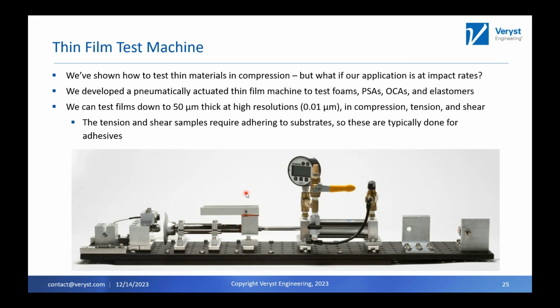So I want to introduce you to what we call our thin film test machine. This machine was developed over years to test things like foams, adhesives, including PSAs and OCAs, and other soft materials at high rates. We often test materials down to 50 microns thick, with very high resolution, 0.01 microns. We can test thicker materials, up to about 5 millimeters thick if we need to. But if we're getting that thick, it might be worth it to go to one of our other machines.